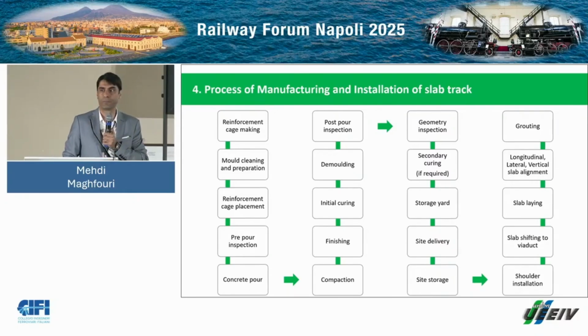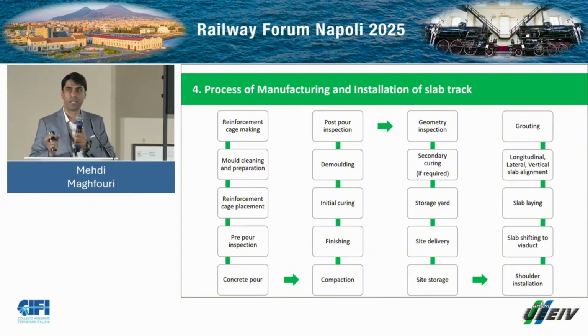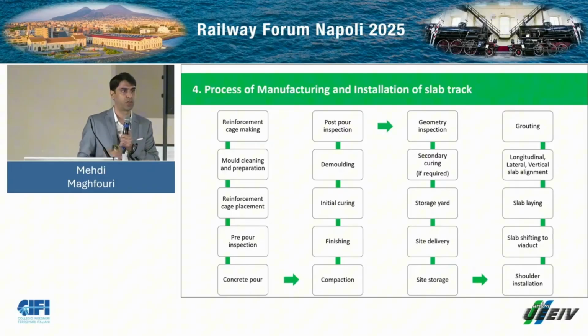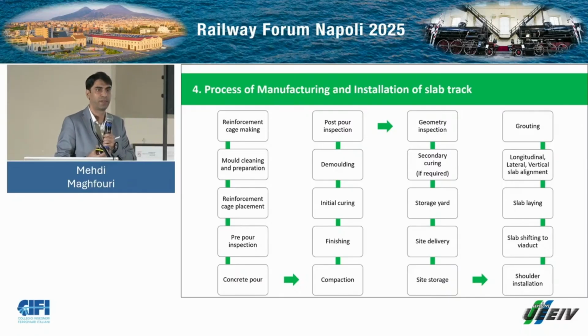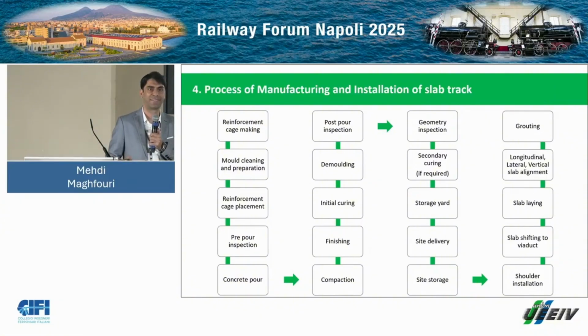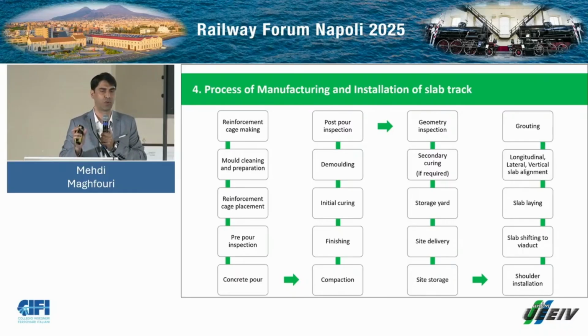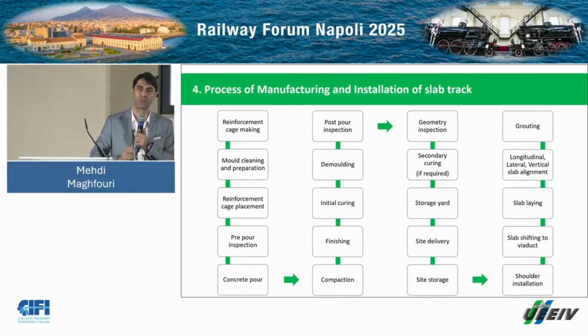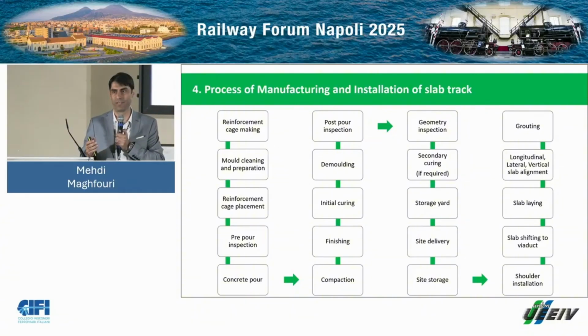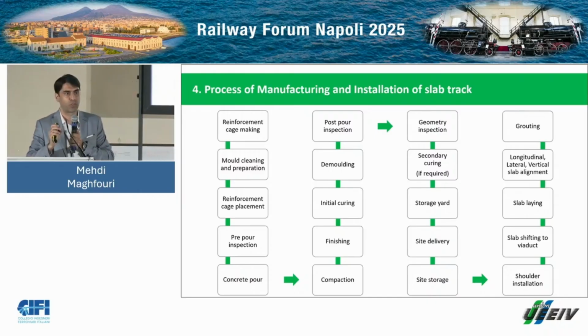After pouring, of course, proper vibration should be in place, then finishing of the concrete surface, and then the initial curing. Initial curing could be just a normal curing, just covering the concrete surface, or could be steam curing. Steam curing up to about 55 degrees, especially in Europe. In order to have a faster demolding process, we need steam with a temperature between 50 to 55 degrees. However, in what we are practicing under the Japanese system in India, we can go up to only 40 degrees. And the reason could be to avoid any micro cracks inside the concrete.